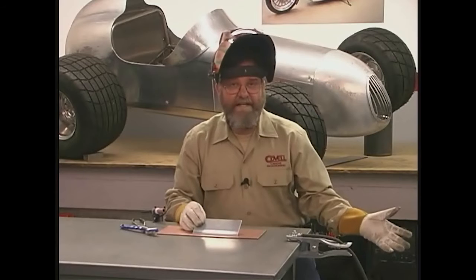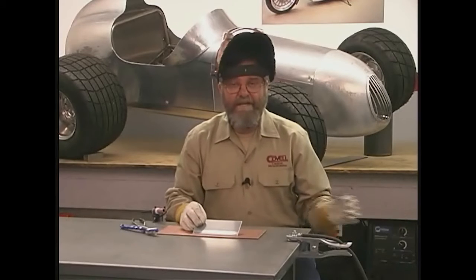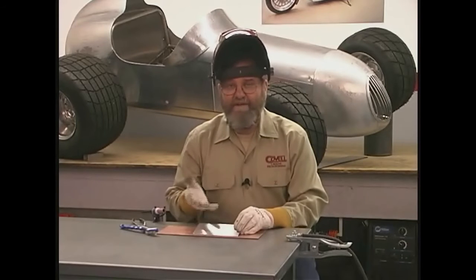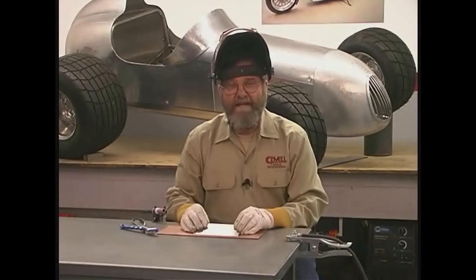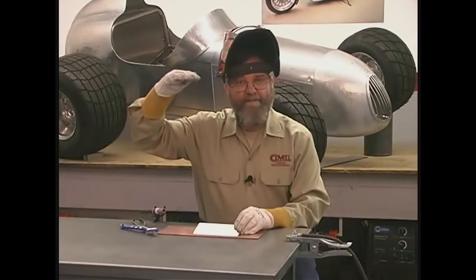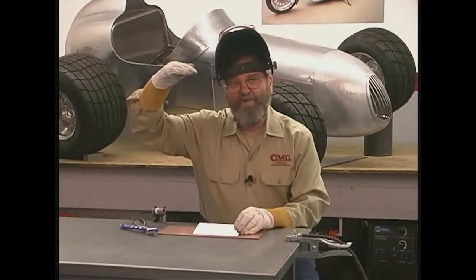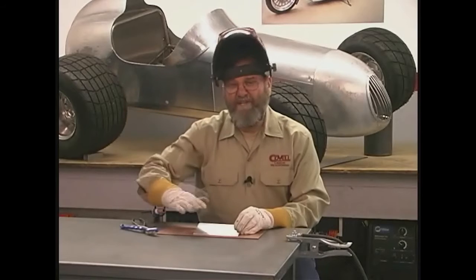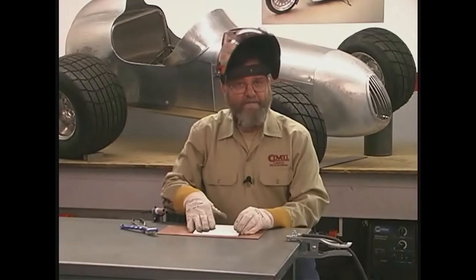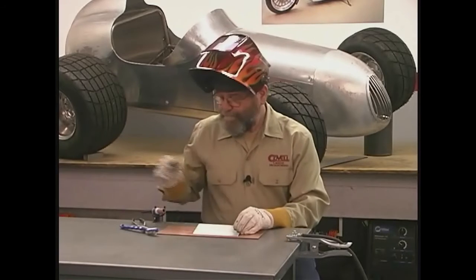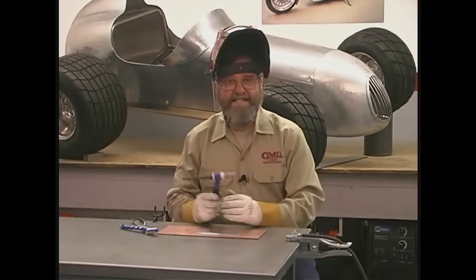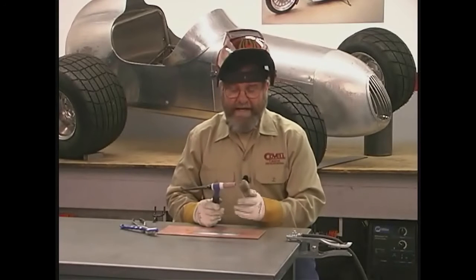Because we're welding aluminum, I've set the machine a little differently. It's on alternating current. The amperage is set to 90. I've set the frequency to 120 cycles per second. That's a pretty good all-around setting for aluminum. I've set the balance to 75%, quite a bit stronger toward penetration because we don't need very much cleaning on fresh aluminum like this. The argon flow is set to 18 cubic feet per hour, and I have 10 seconds